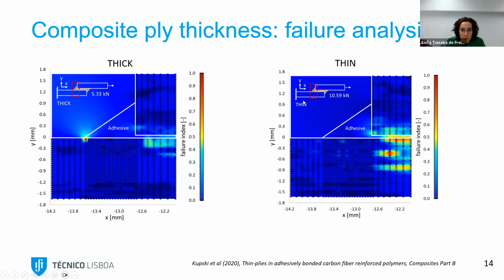Now, if we look at the same geometry of the adhesive, but now with thin plies, so we had many more plies in the substrates, what we see is that the hotspot, the stress concentrations, move away from this area, and they concentrate more in the region through the composite ply thickness. So first of all, we have more points, not only one isolated, but more points in which the stresses are concentrated, and they are also deeper into the composite.